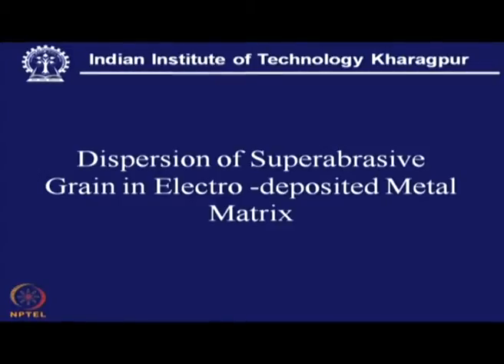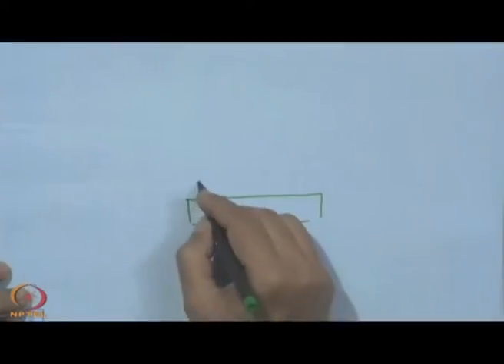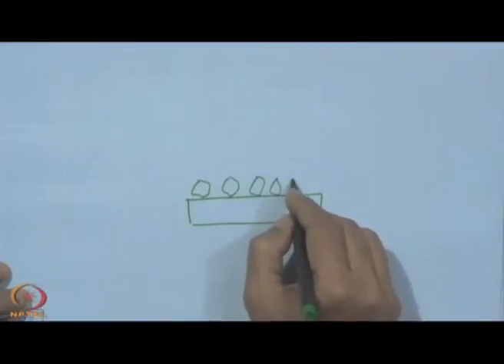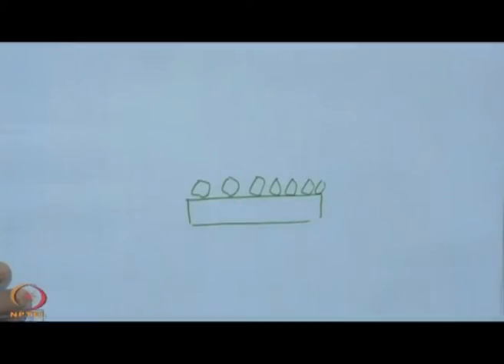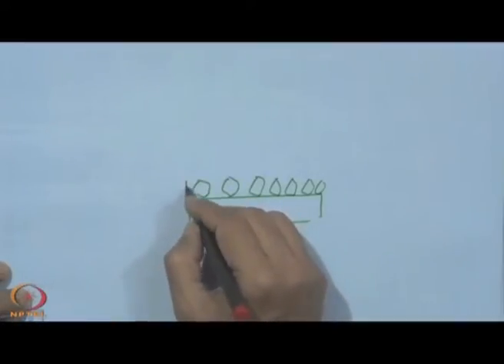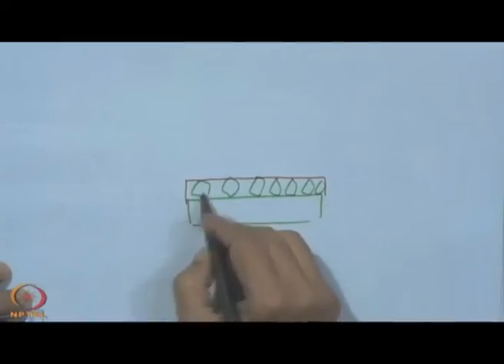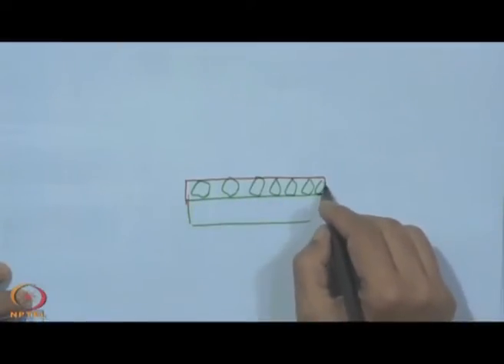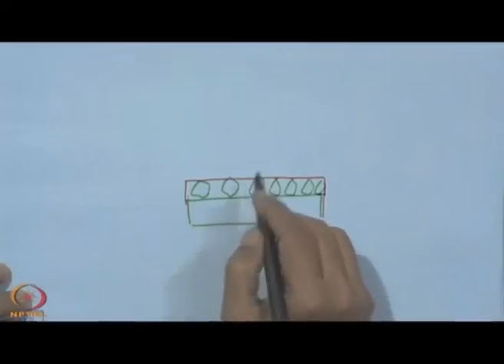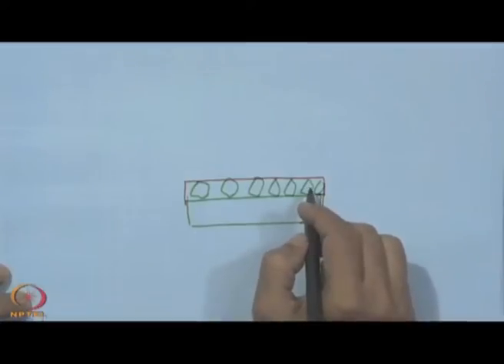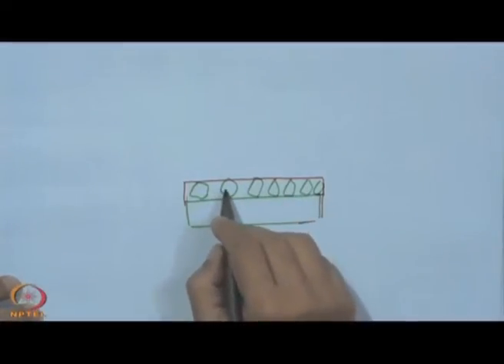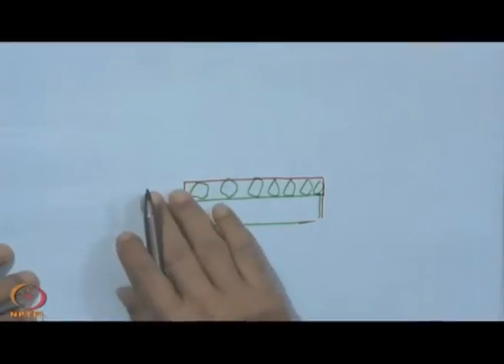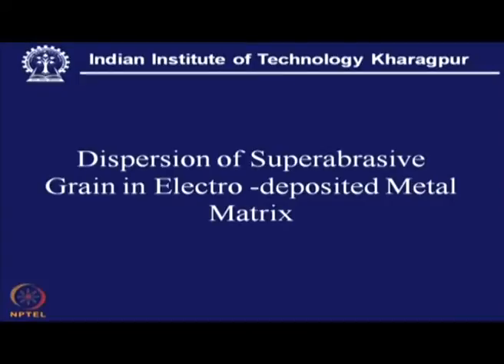Now, this can also come as a dispersion of super abrasive grain in electrodeposited metal matrix. That means, the whole thing can be covered. So, these are the grits with a very high concentration, and we can have a composite coating. That means, in this case the coating can go up to this point. So, here we have a coating which is composite in nature. That means, we have abrasive grit dispersion with high concentration, but that is well dispersed in a metal matrix. So, in this case the grits are not projected, but are totally covered. So, this is the dispersion of super abrasive grain in electrodeposited metal matrix.